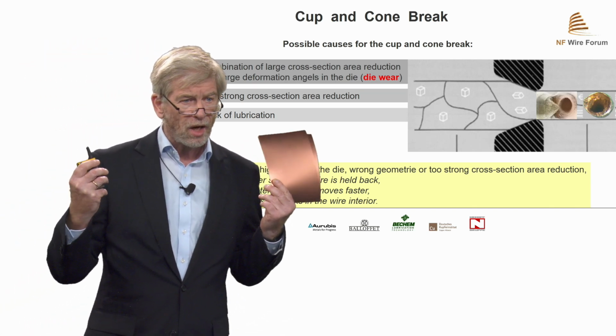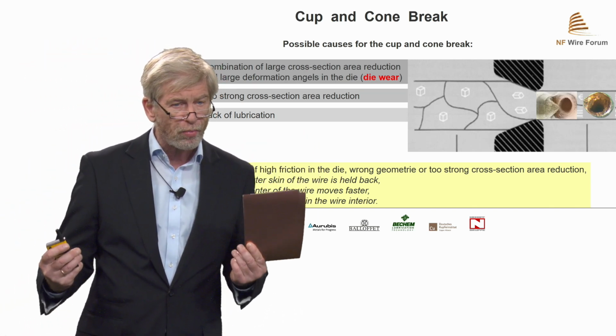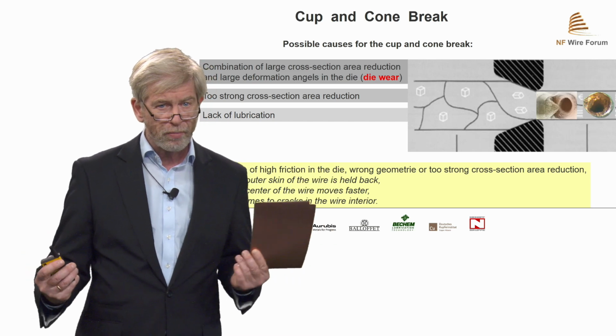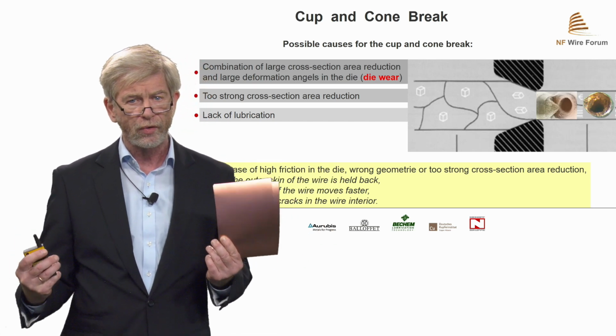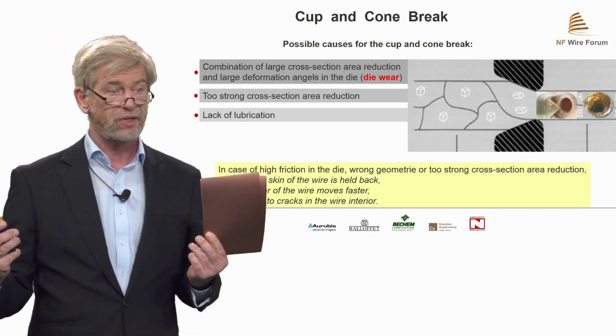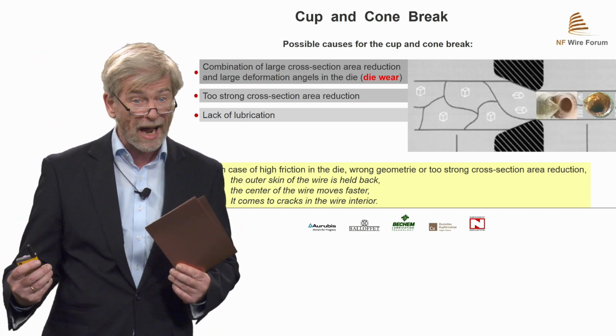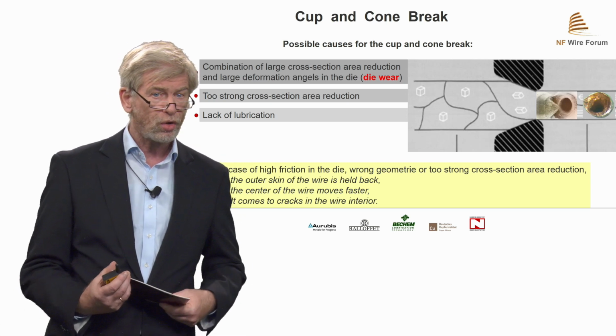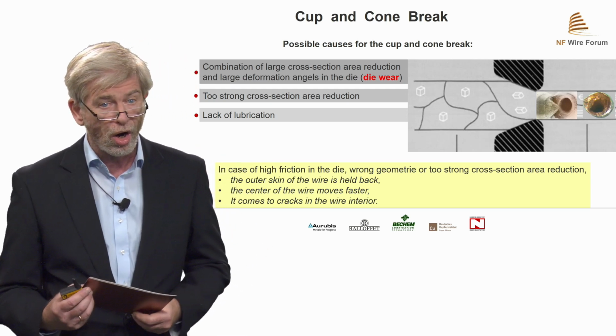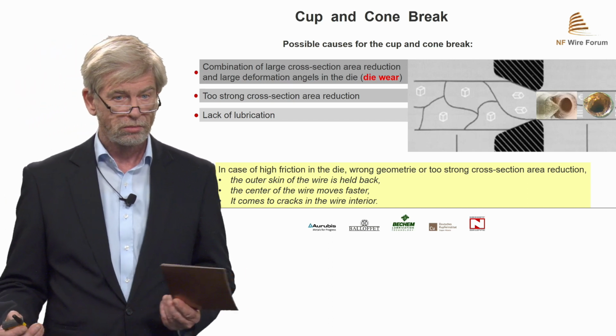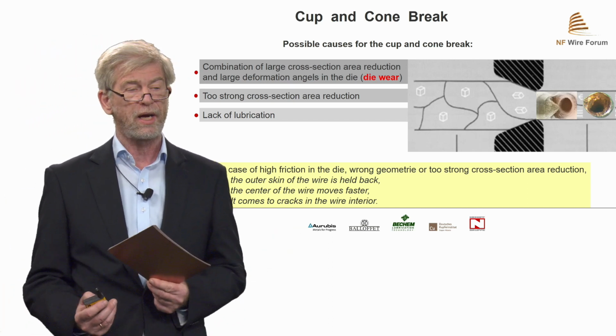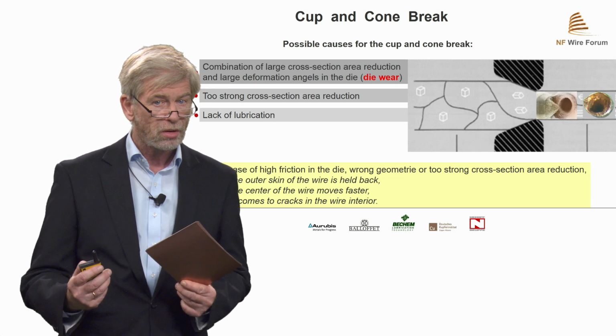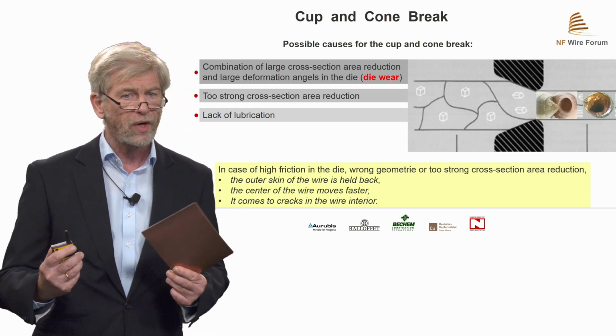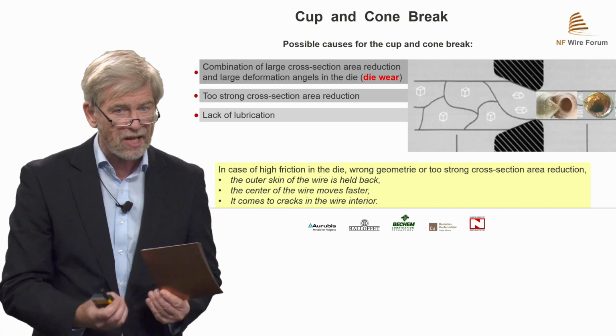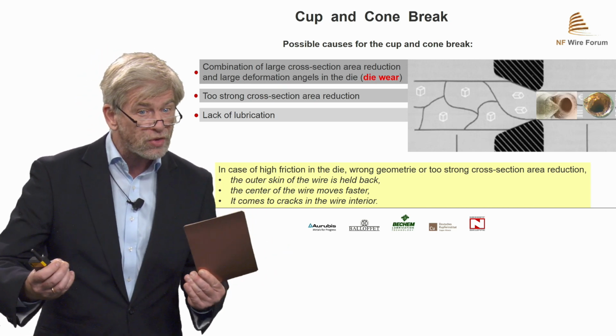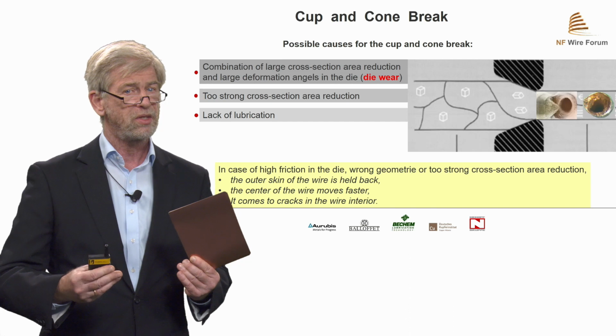But now let's see possible cases for the cup and cone break. There can be a combination of large cross-section area reduction and large deformation angles in the die. That's called a die wear. Too strong cross-section area reduction or lack of lubrication. In case of high friction in the die, wrong geometry or too strong cross-section area reduction, the outer skin of the wire is held back. The center of the wire moves faster, it comes to cracks in the interior.